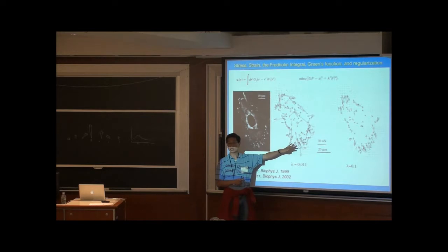Now, of course, that constraint cannot be perfect, because if we impose it to definitely sum to 0, but at the same time we say that the forces that we solve don't have to perfectly match the strains, it will never perfectly sum to 0 either. So what we need is something that says it's sort of close to summing to 0. And again, we have to use one of these lambdas that lets us dial up how much we're willing to tolerate it not summing to 0 versus it does sum to 0.